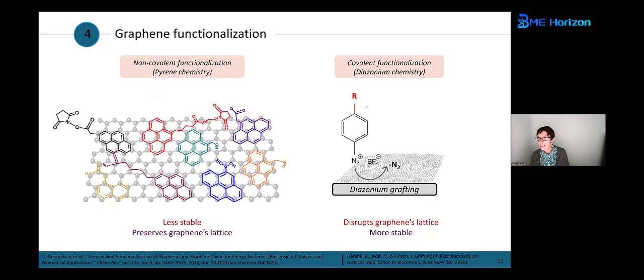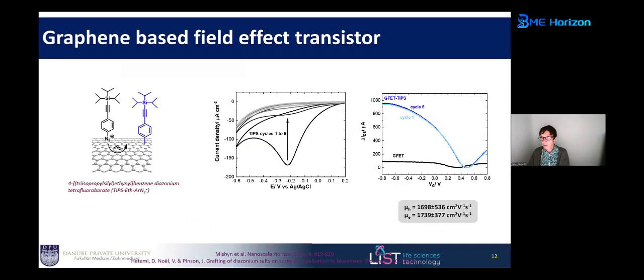So let's start with this covalent functionalization, where we often use diazonium chemistry to covalently link and form carbon-carbon bonds on this graphene by taking off this nitrogen function. This chemistry is known over years. When we do diazonium chemistry, we can also form polymers because it's a radical chemistry. So what one normally uses is a diazonium ligand which is a bulky group. That means you limit the formation to a monolayer. And this you can easily see here in the cyclovoltammograms.